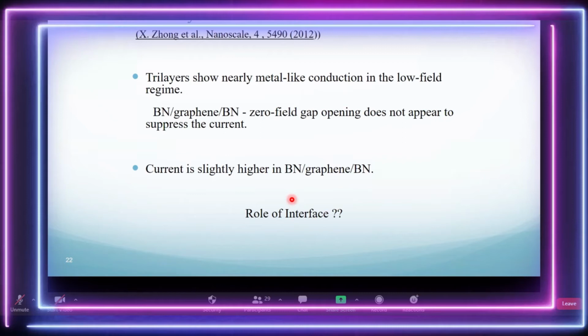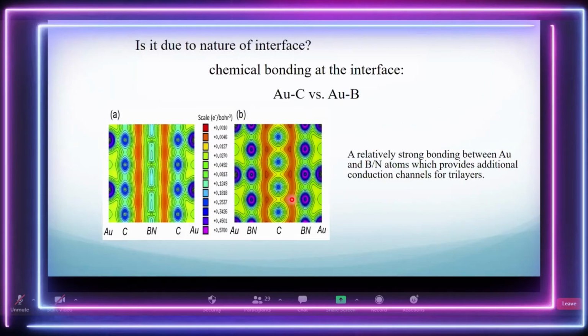So you go down and plot the charge density. And this figure really tells you, indeed, the interface takes over the intrinsic property of the material. Because if I pick a case, graphene, boron nitride, graphene, and these are the contacts, left, gold, and so on. And if you see here, there is a significant overlap of the electron density. It means gold is really forming a strong contact with carbon.